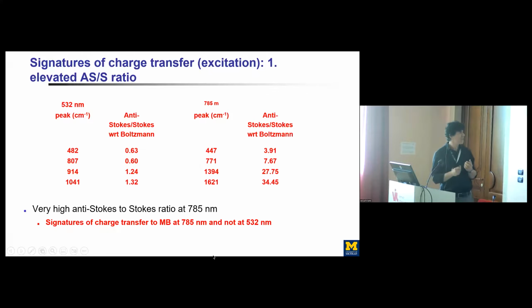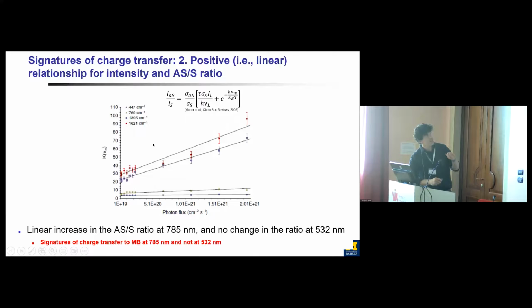So what this is telling us is that at 785, we have some condition that's causing this molecule to get hot. And at 532, even though we are shining more energy, we are putting more energy in the system, there's really no thermal heating of the molecule itself. We also monitored again how this anti-Stokes to Stokes ratio behaves as a function of photon flux, as a function of intensity. And what you see is this linear dependence where the more energy you put in the system at 785, the more of this heating of this molecule you get. So this is again a signature of a charge transfer process to MB.